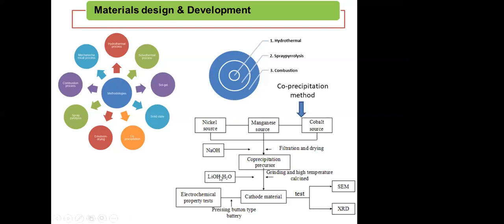Once you grind the precursor with the lithium salt, then after calcination at a higher temperature of nearly 700 to 800 degrees, you get your cathode material, and then this cathode material will go for testing. There are two parts. First is phase analysis, and then morphology, because phase and morphology play a big role in the performance of the cell. And once the phase is formed, then you go for electrochemical property tests.